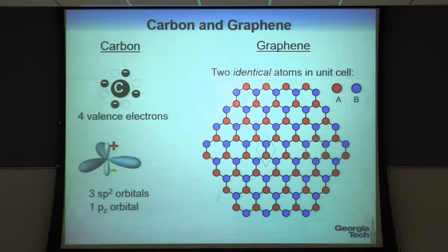So graphene, you probably are aware, is just a single sheet of carbon atoms in the plane. They are sp2 bonded. That's these bonds sticking off over here. But sticking out of the plane, there's a p orbital, the pz orbital, which I'll remind you has a phase. It's positive phase over here, negative phase over there, or vice versa, okay? And in fact, the electronic properties near the Fermi level are determined by the bands that are formed by overlap, that's pi band overlap, of these pz orbitals on each one of these sites.